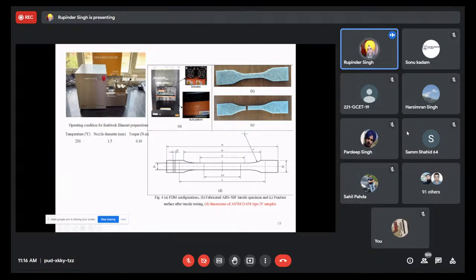Then this was fed to the 3D printer, an open source 3D printer with a 200 cube size. I can print over here. Finally, the tensile coupons as per ASTM D638 were prepared. This is the Type 4 standard that has been used, in which the dimensions are mentioned. Now these are the samples after the UTM testing, in tensile condition only.